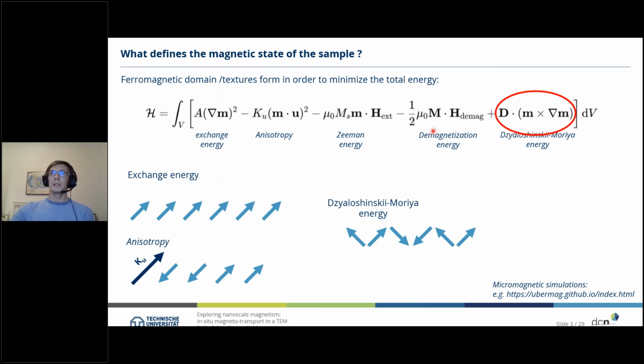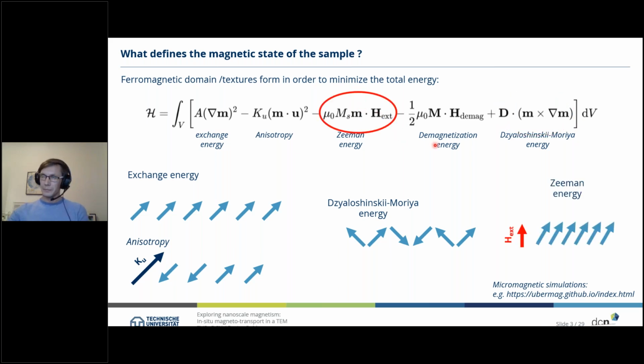And then we have the demagnetization energy, of course, which leads to the formation of domain patterns and closed domains at surfaces, for example. But the main thing which we can control externally, and which gives us a knob to adjust the magnetic configuration of the sample, is the so-called Zeeman energy, which depends on the magnetization of the sample multiplied by the external magnetic field. If we have a magnetization state which looks like that and we apply a magnetic field, the magnetic moments will align with the external magnetic field to minimize the total energy.